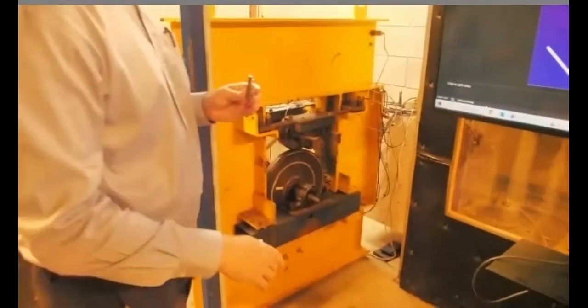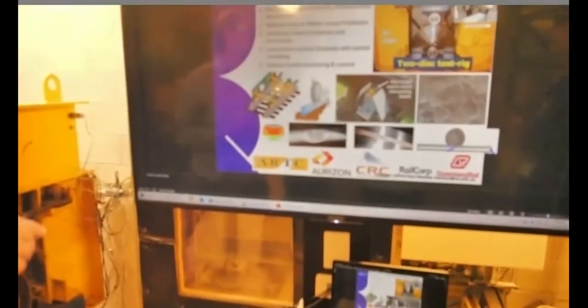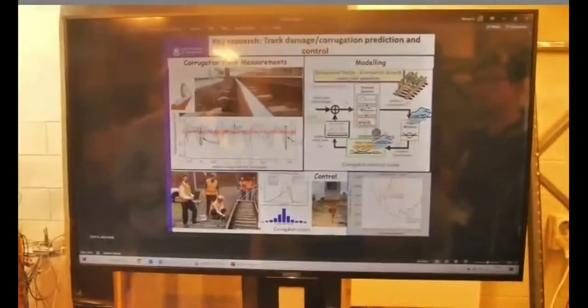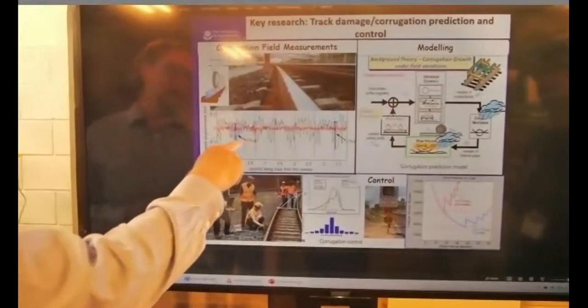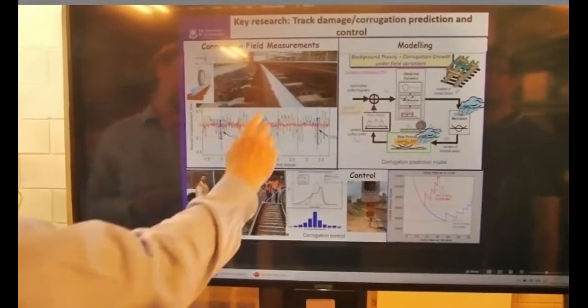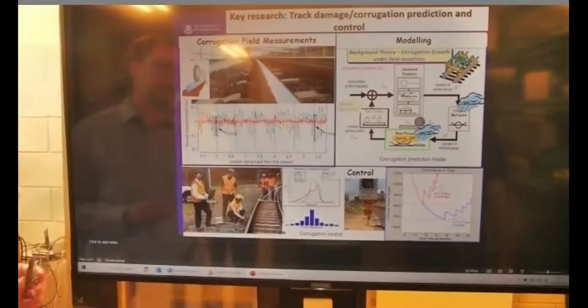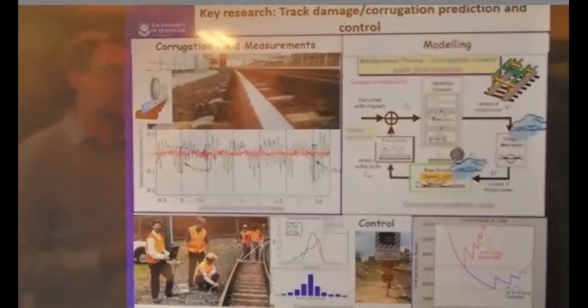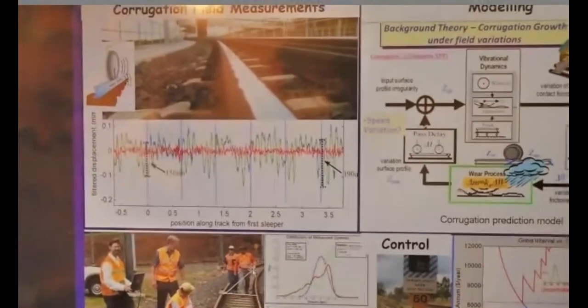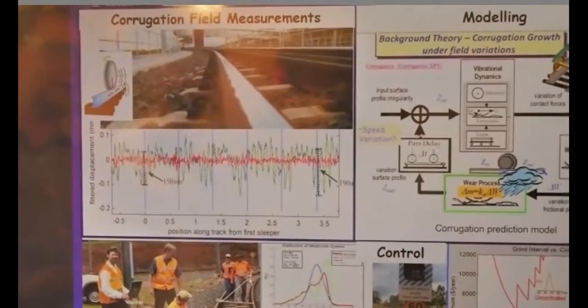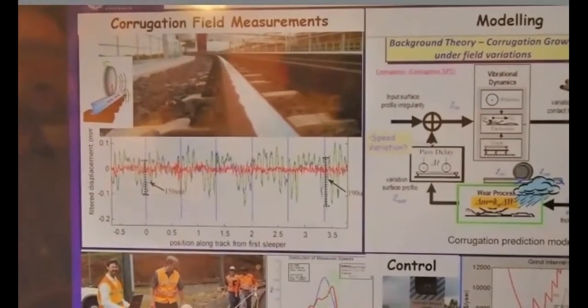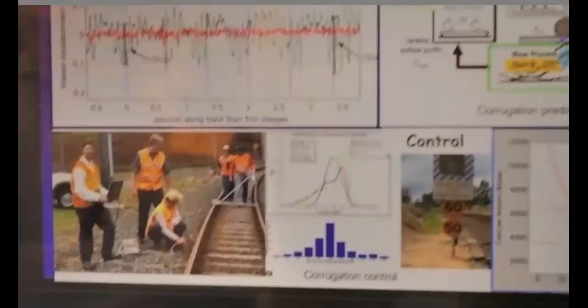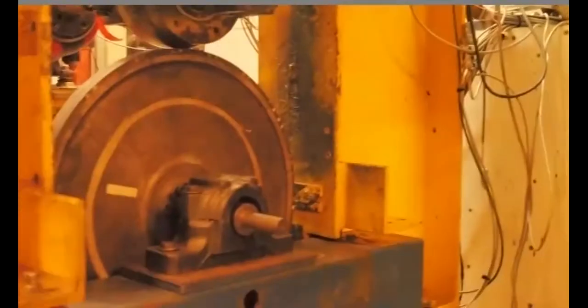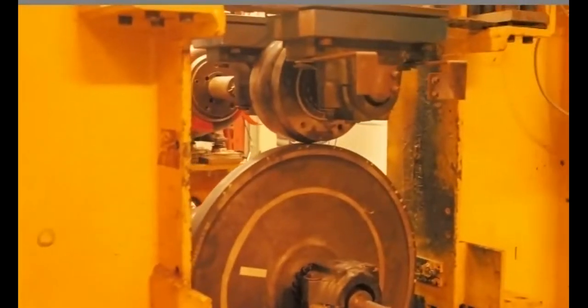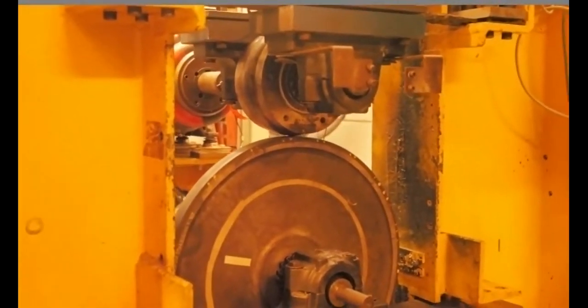I think we have a measurement here. Xing, if you could jump to the... we can see a measurement here of the order of 150 microns. If you get down low to the rail, you can see that wavy pattern occurring. At that amplitude, the rail needs to be reground very quickly due to large vibrations and noise. So we've investigated the modelling and control of that process, and we've been able to recreate the corrugations, which take over a year in the field, on this test rig in the order of 10 hours.